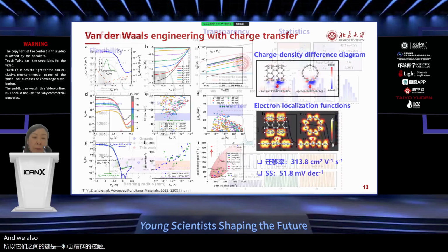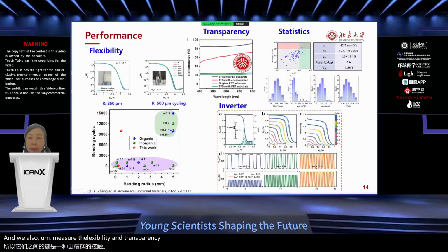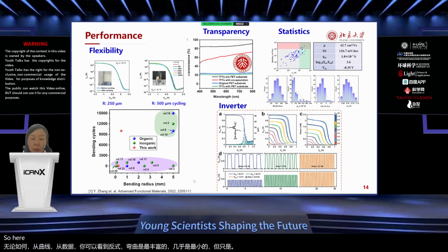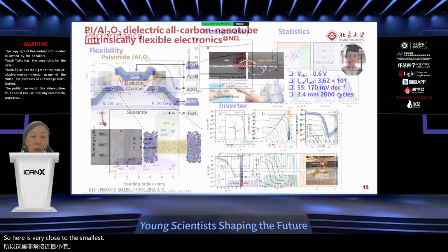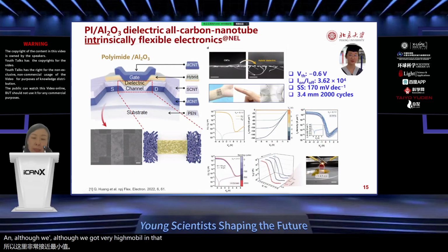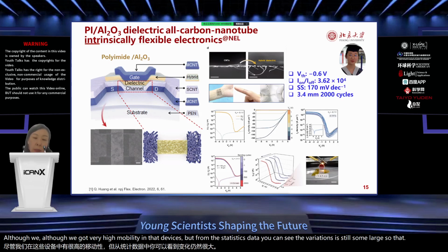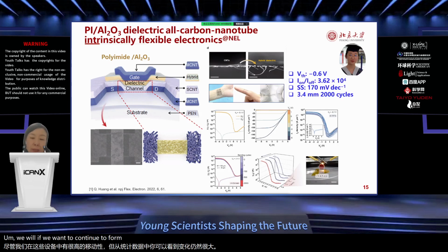And we also measured the flexibility and the transparency, the statistics data, and also the inverter. Anyway, from the curves, from the data, you can see the bending reaches almost the smallest, or at least very close to the smallest. Although we got very high mobility in these devices, from the statistical data you can see the variation is still somewhat large. So if we want to continue to form circuits, we will further improve the statistical data, and also we need to improve the integration level.